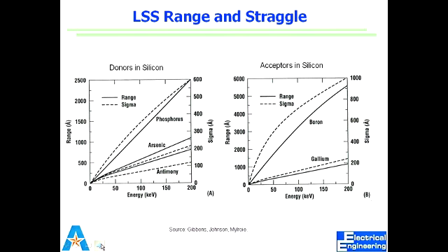If the whole loss mechanism is through electrons, size doesn't matter. So boron will have more of SE. Exactly. So now, if the ion is losing energy to the nucleus, then of course the size matters. So it's a factor of what the loss mechanism is, right? So that will define the straggle. That in a way tells us which shows more sigma, more straggle.